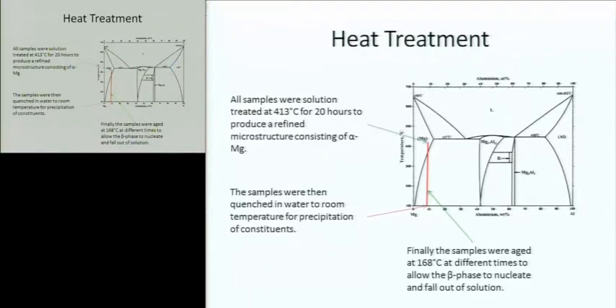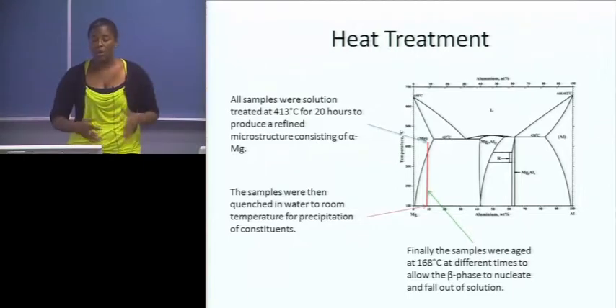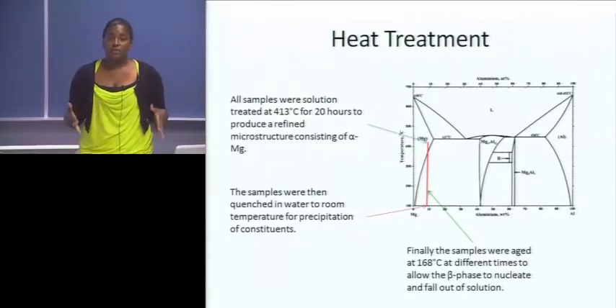So in this diagram, all of my samples were heat treated using the ASM T6 method. In this method, the materials are solution treated at 413 degrees Celsius for 20 hours to produce a refined microstructure consisting of alpha magnesium. Then the samples are quenched in water at room temperature to precipitate out the constituents. Then finally, the samples are aged at 168 degrees Celsius at different times to allow the beta phase precipitates to nucleate and fall out of solution. So the aging time is what was different in my project.